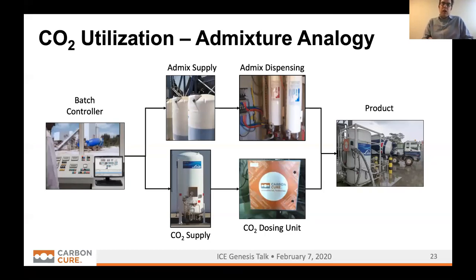How this works is best described as an analogy to a concrete admixture. You start in the concrete batch system. When a new load of concrete is required, the batcher will say, for example, I need 8 cubic meters, one truckload of concrete, with this specific mix design. In this mix design, I need certain admixtures. The batch controller then communicates with the admixture supply, which dispenses admixtures into the concrete mixer, either the mixer or the truck. Likewise, we can have a mix design that includes carbon dioxide. When that mix design is made, a signal is sent to the CO2 supply and the CO2 dosing unit to start putting carbon dioxide into the mixing process. It's injected just like an admixture into the concrete as it's being produced.